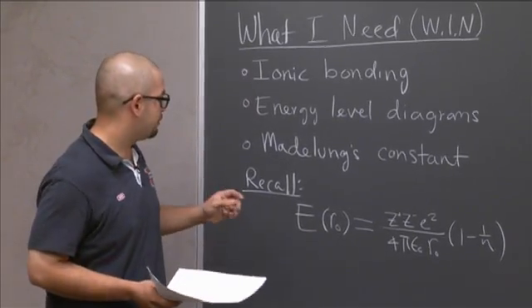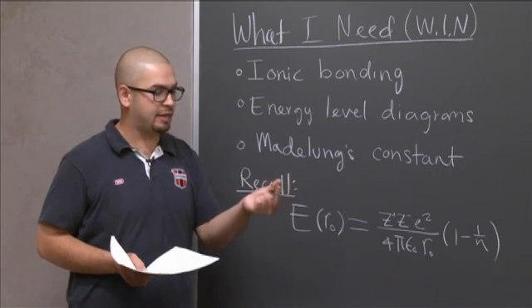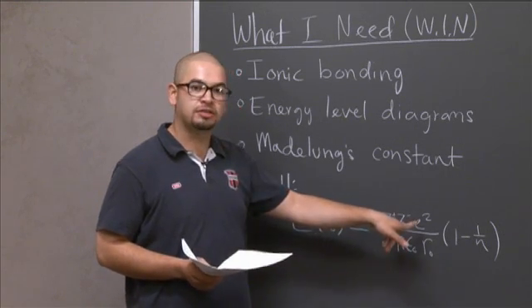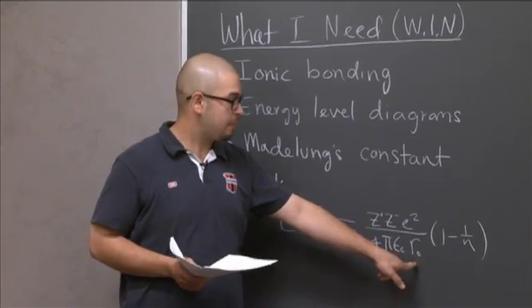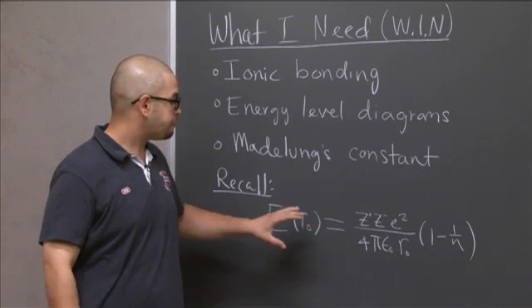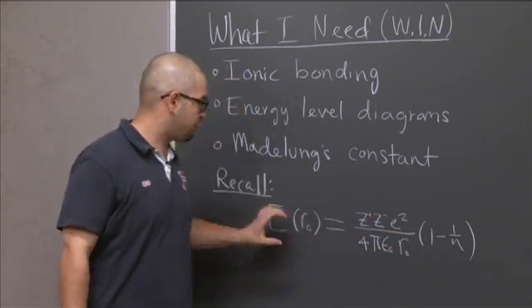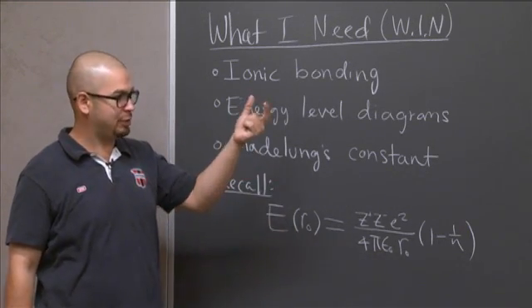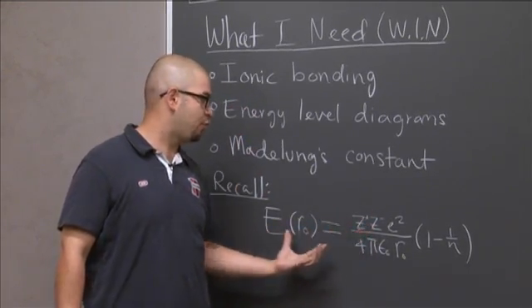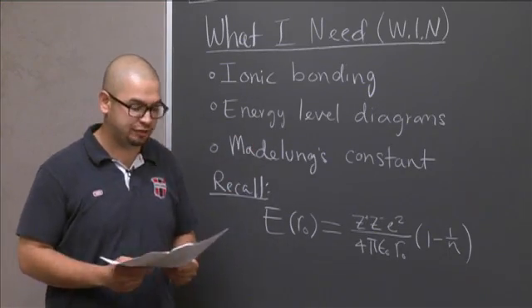Now, if you recall from lecture, there's an important equation that actually describes the energy between two ions, a cation and anion. And this energy is directly proportional to the product of the two charges and inversely proportional to the separation distance between them, multiplied by some constants. So what does this mean? The fact that it's directly proportional to the product of your two charges means that your energy for anything that ionically bonds is going to be negative, because your Z minus will be negative. And that's what dictates stability, how negative the energy is.